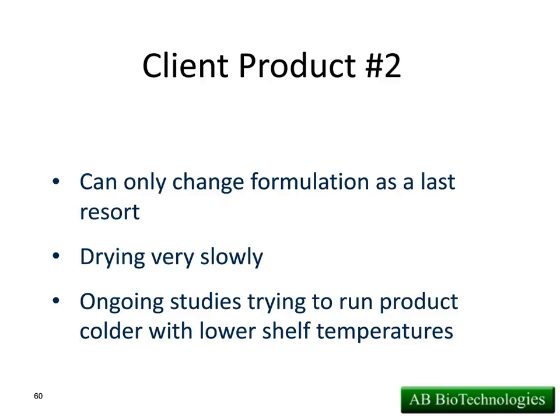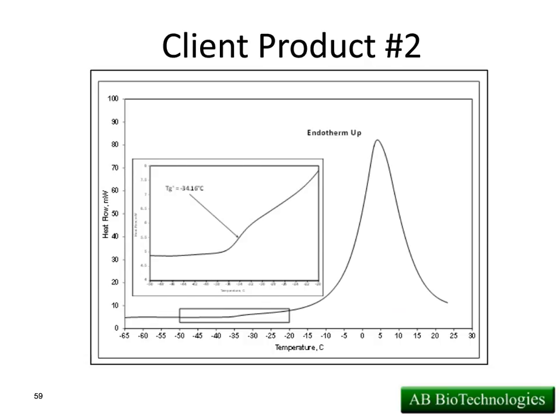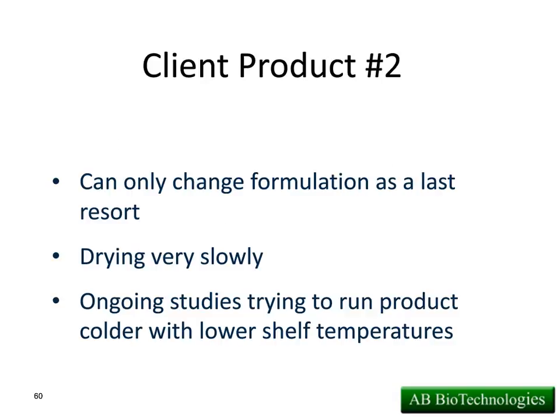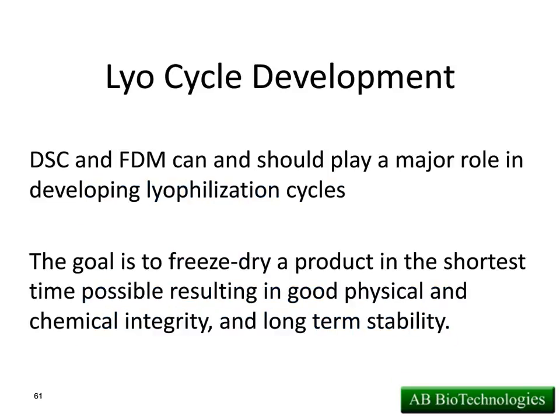Okay, so we said, is there any way we can improve that? In this particular case, too, I can't remember if it was this client or not, it was a partial batch failure. And the problem was they were using an older freeze dryer. Like Tian mentioned, freeze dryers have been around for years, and some of the older ones don't have the latest and greatest in the engineering. So this particular dryer was older, it couldn't keep the product cold enough below its glass transition temperature, negative 34. So some of the vials that were exceeding that temperature a little bit were going through a collapse. So our recommendation was, you need to go to a newer freeze dryer that can keep your product at a lower temperature. So in summary here, the DSC and freeze-dry microscopy can and should play a major role in cycle development, not only understanding what is in our formulation, crystalline or amorphous metastable, but again, in cycle development.